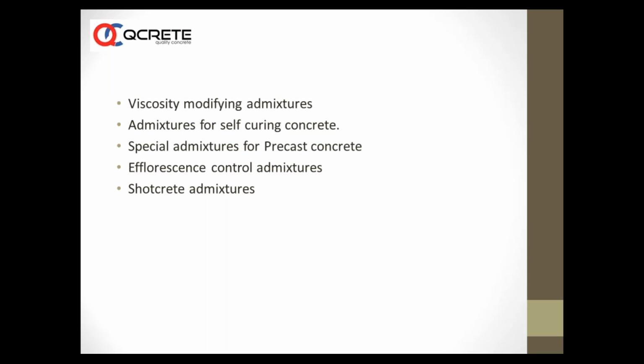You have special admixtures for precast concrete where you need very accelerated strengths, high early strengths, where 12 hours 12 MPa, 12 hours 16 MPa, these kind of strengths are required. Here you need a high degree of water reduction, achieved by a PC based admixture, with an inbuilt accelerator blended into it to enhance the hardening process, so early strengths are gained.